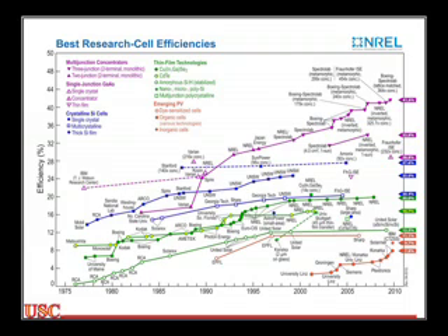So if I absorb a blue photon, what happens in silicon is within a matter of a picosecond or so, the energy that I deposited into the silicon with the blue photon is all dispersed as heat, and I now have an energy gap exciton. So I've got something at sort of the purple line I show here. And so all those high energy photons all thermally relax to the lowest energy state. And so if I take my AM 1.5 spectrum and correct it for this energy drop, I get the green part of the curve. So that's all I collect, that green part of the curve. That's the best I can do if I recalibrate this for the energy I can get.